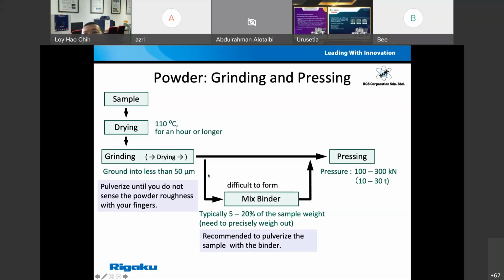But if your sample is very difficult to form a pellet, this is the time that you need to mix your samples with binders. Okay. So in terms of binders, there are a few types of binders that you can select, like boric acid. You can either mix it with boric acid, or you can use boric acid to bind it at the side, then the rest is in the center. The sample is in the center for the measurements. Or some use, we mix it with some cellulose powder, or some we mix it with plastic powders. So all those are actually analytical grade powders with very, very low contamination. Okay. So once everything is mixed, then we put it into the press, then we can press it into pellets.